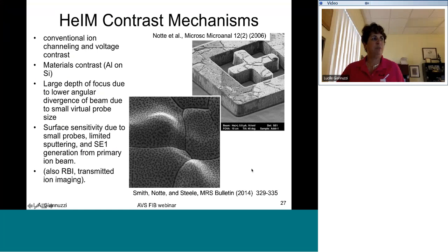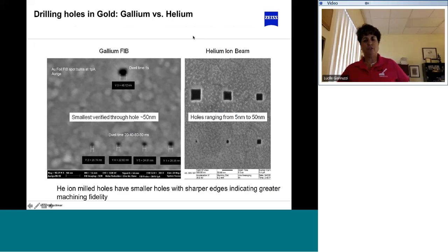The advantage to the helium ion microscope, contrast mechanisms, and actually ion beams in general, is you do get the conventional ion contrast, voltage contrast. You get your conventional material contrast. You get the large depth of focus, and this is, again, generic to most ion imaging. Ion imaging, in general, is extremely surface sensitive, but with the helium ion microscope and the very small probes, this limits sputtering. And ion imaging is really a pure secondary electron signal. You can also get Rutherford backscattering ion imaging and some other types of imaging. So it's really good for imaging.